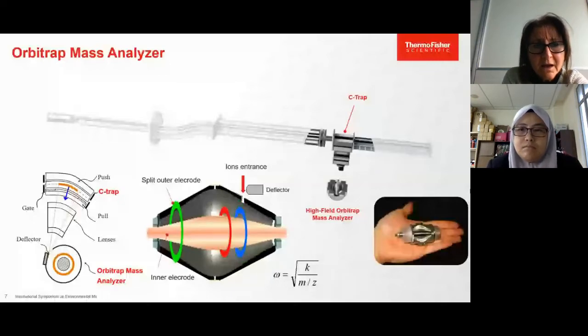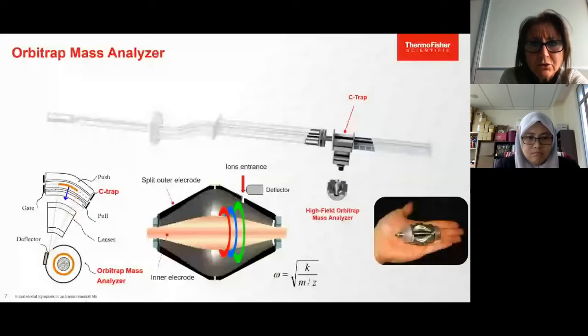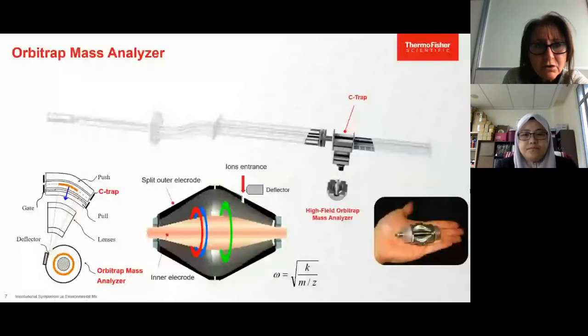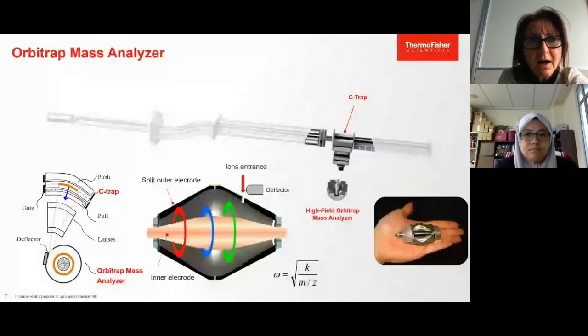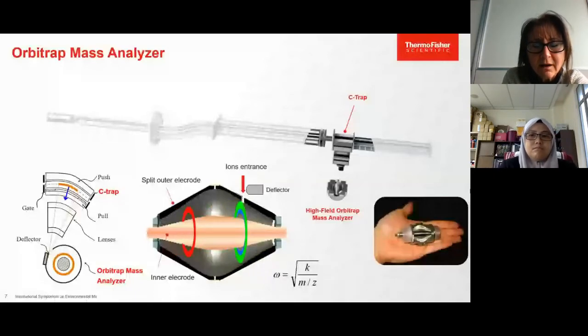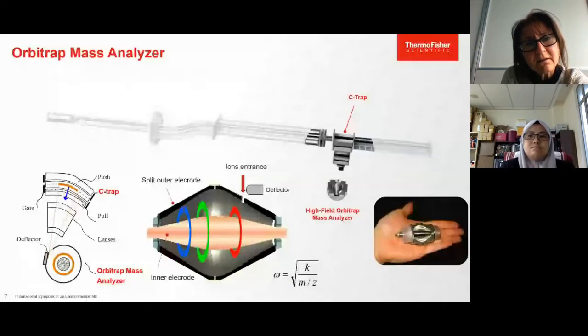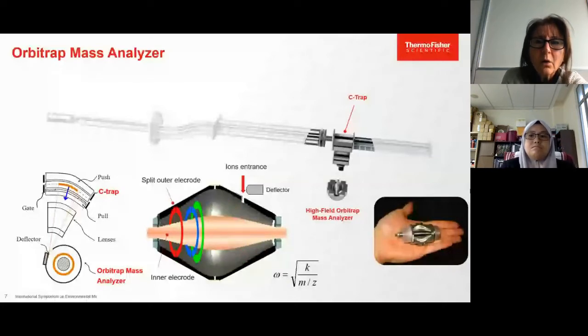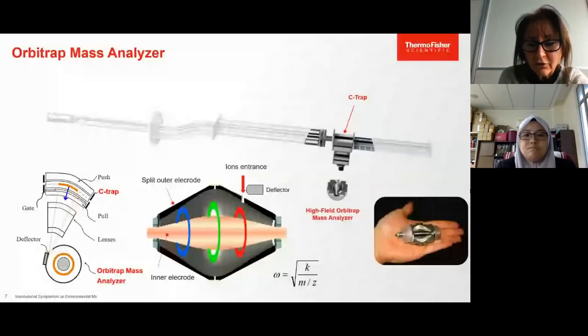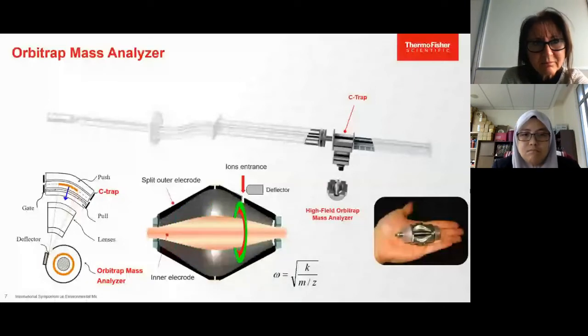As the ions enter the Orbitrap, they are squeezed towards the inner electrode by its electrical field and start rotating around it. Additionally, the bell-shaped outer electrodes induce an axial oscillation whose frequency depends only on the ion mass-to-charge ratio. And therefore, such oscillation frequencies are used for the ion mass determination. Worth noting that the signal is due to the current generated by the oscillating ions, and it is measured at the outer split electrodes. So there is no electron multiplier in the system, so there is no more need for electron multiplier replacement.